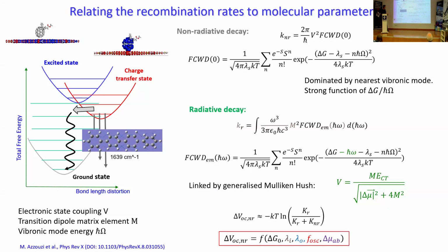But the point here is that the non-radiative decay rate is quite fast. And that rate is quite fast because the excited states can have their energy dissipated to ground relatively efficiently through quite high energy vibrational modes of the material. And those high energy modes are coupled to the electronic excited state. And that means that they can dissipate the energy relatively easily.